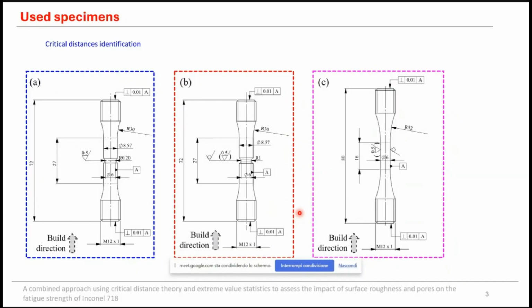The one on the left had a sharp notch, and it underwent a turning machining operation before the fatigue test in the zone around the notch to reduce the impact of surface roughness on the fatigue strength. This surface condition was named machined. This specimen was only used to identify critical distances, while the specimen in the middle had a blunt notch, and it underwent fatigue test under two surface conditions.